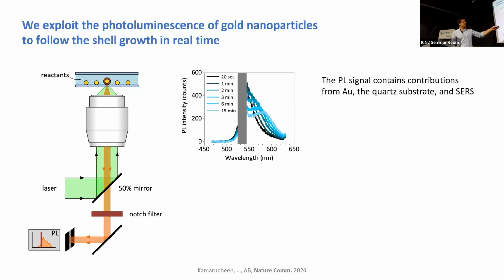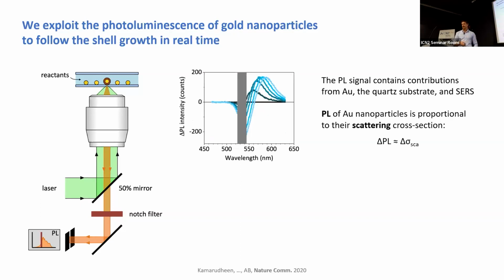And the reason for it is because this inelastic light scattering contains signal from the photoluminescence of the gold, any photoluminescence from the quartz substrate, any Raman scattering that can be in the solution. And so what my PhD student suggested was, well, why don't we subtract the initial spectrum from all the other ones so that the standard background contribution can be canceled out. And when you do that, you get a trend like this.